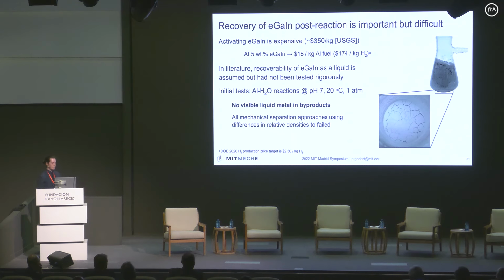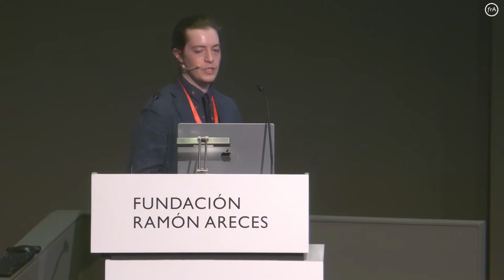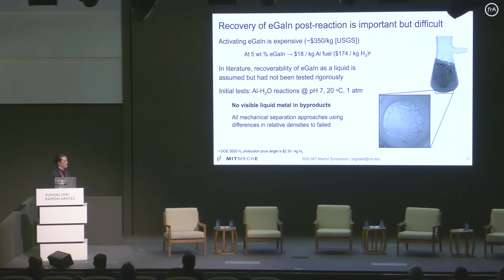But going back to this main problem of how do we recover the gallium and indium. Again, gallium and indium are very expensive. At this eutectic mixture, it's about $350 per kilogram. So if we were throwing that away, we'd essentially be generating hydrogen at $18 per kilogram of aluminum. Which is not great, and that equates to $174 per kilogram of hydrogen.